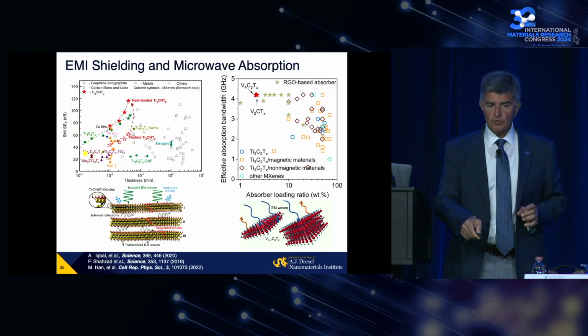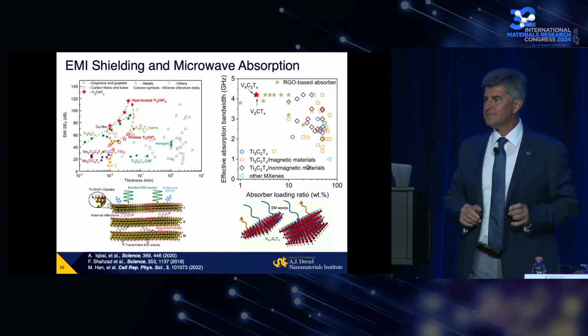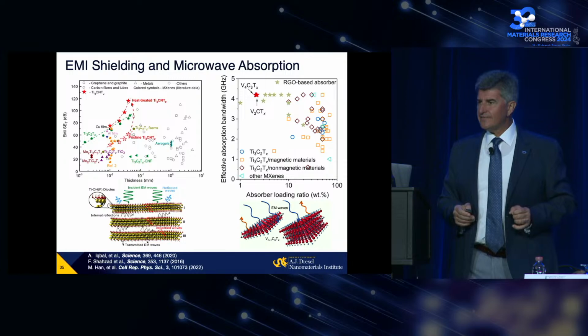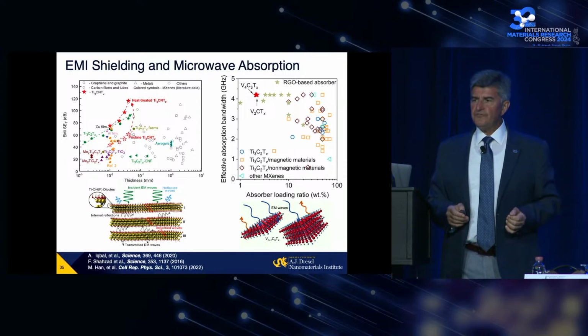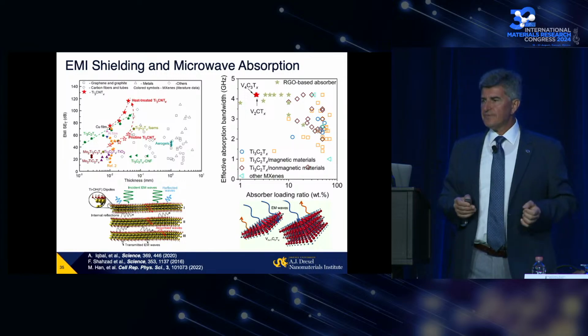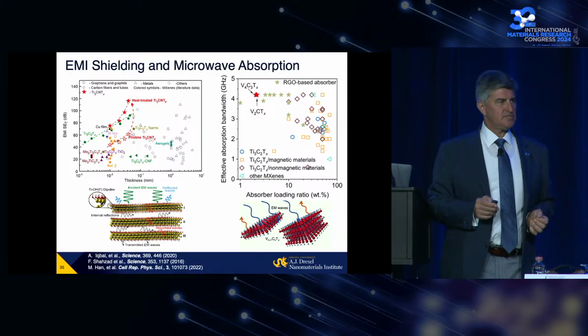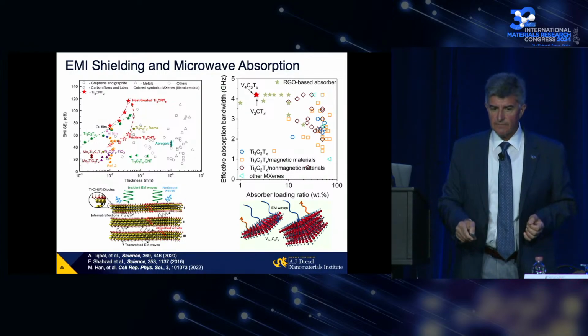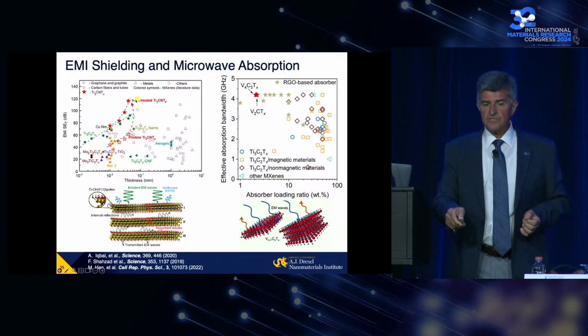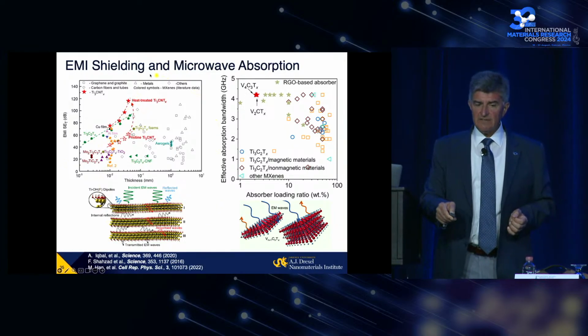But remember, I showed we can make freestanding 1-micron films providing shielding for everything. We can spray coat a 50 nanometer film and provide 99% shielding of the signal, sufficient for the majority of applications in everyday life or the Internet of Things. This material, like titanium 3C2, reflects electromagnetic waves. Titanium 3CN also does, but it actually at the same thickness outperforms copper, which is orders of magnitude more conducting. So there are different mechanisms of interaction with electromagnetic waves.